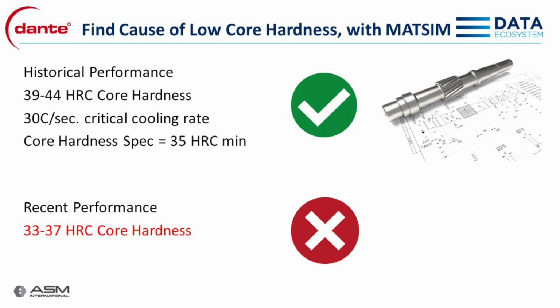First things first, you want to know that your process is in control. You've checked your quench and still hitting the 30 degree per second cooling rate that works well with this part. That's good news. You now wonder if it's the steel. Looking at the mill certs didn't show anything obvious.